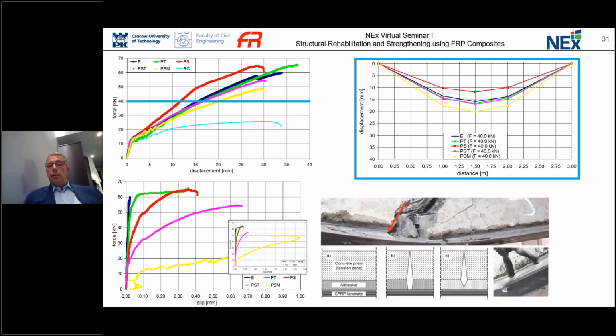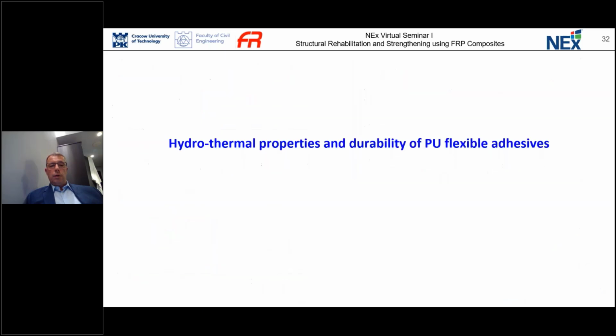Why is it? Because, as I said previously, when we have the stress concentration, the crack goes through the stiff epoxy resin immediately and attacks the composite material, causing stress concentration. If we have higher stress, we have, of course, higher elongation. In the case of flexible material, we stop the crack in the adhesive layer and redistribute the stress more evenly. So in this case, the peak of stress is lower, so also elongation of the composite material is lower. So in this case, the confinement effect is more promising. This is presented here on the graph.